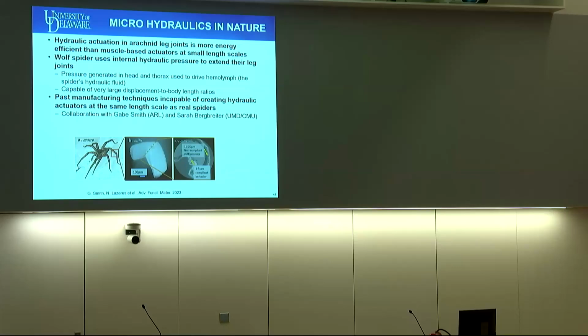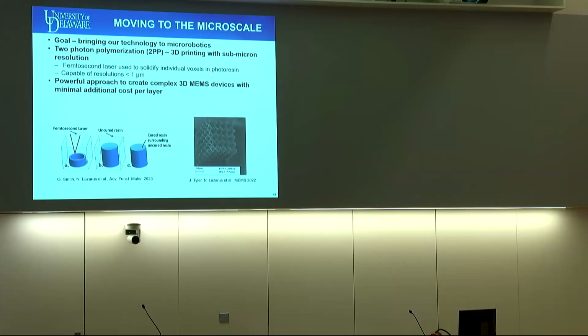But the challenge is that working with fluids at this particular length scale is very difficult. It's hard to push a liquid into a very small feature. And so, working with colleagues both at Army Research Laboratory as well as Sarah Bergbreiter, at the time here at University of Maryland, we looked at whether we can develop a fully soft hydraulic actuator, relying on, again, this 2-photon polymerization, the Nanoscribe type of printer that Ryan talked about, to 3D print at sub-micron resolution. We're able to use a femtosecond laser to solidify individual voxels in photoresin and create very complex 3D structures at minimal additional cost per layer.